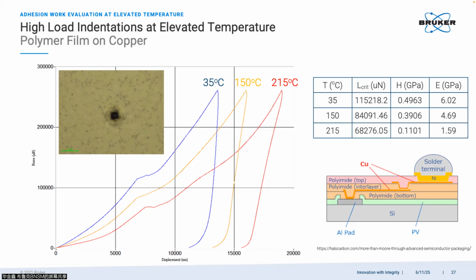And you can see that this is the indentation induced delamination. So this is the delamination point, and this is the critical load. And we have 3 different temperature levels. Obviously, at a high temperature, the required force to delaminate the interface is going down. That means your interface is weaker at high temperature. But the interesting thing is if you take a look at these indentation curves, we use exactly the same probe and apply exactly the same force. And you can see the penetration depth is also highly sensitive to temperature. At higher temperature, the penetration depth is getting higher. That means the mechanical properties of your polyimide layer go down when temperature goes up.